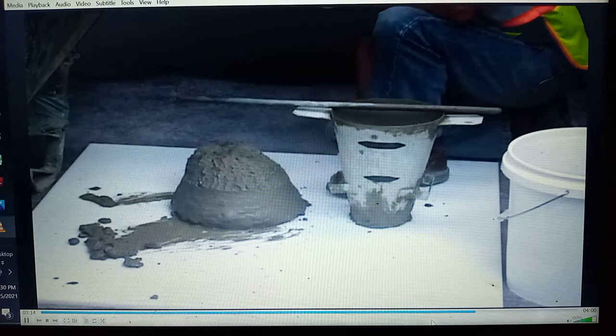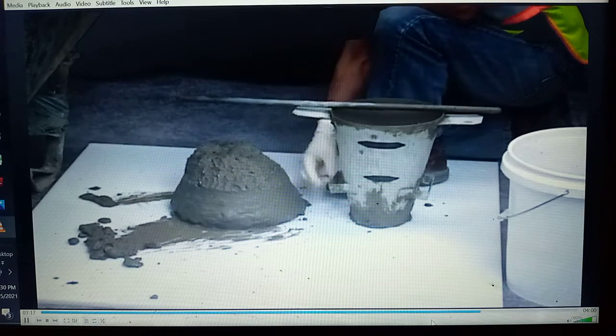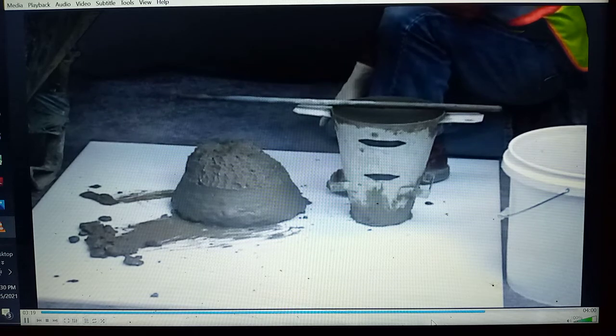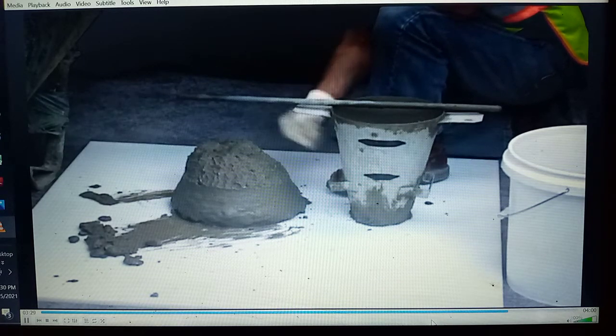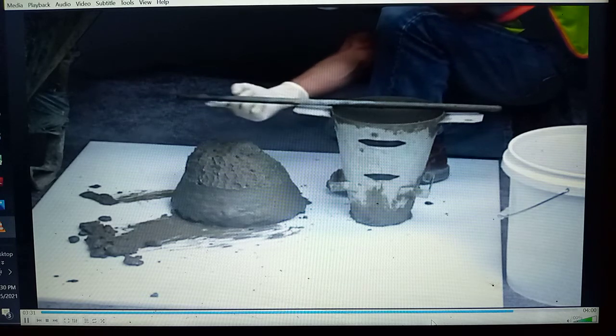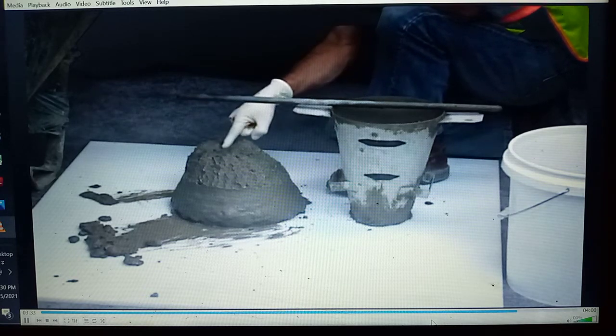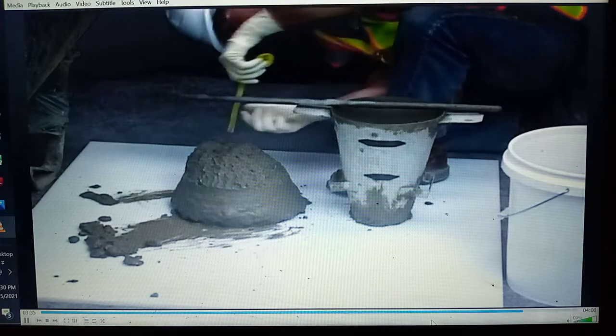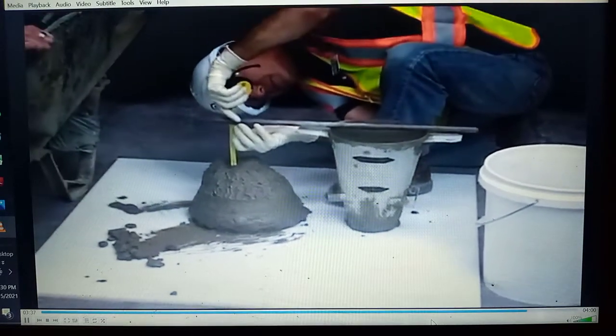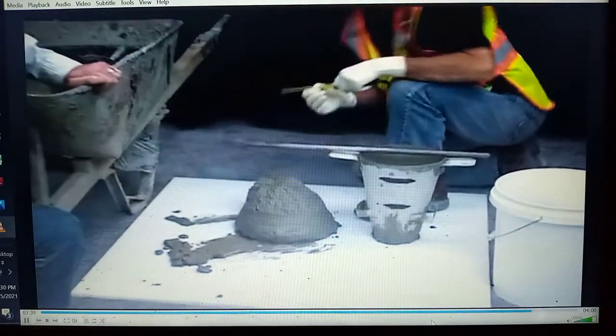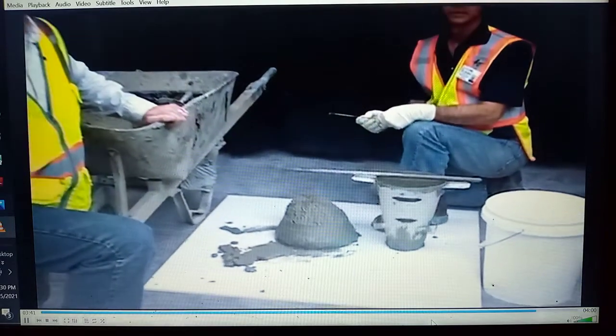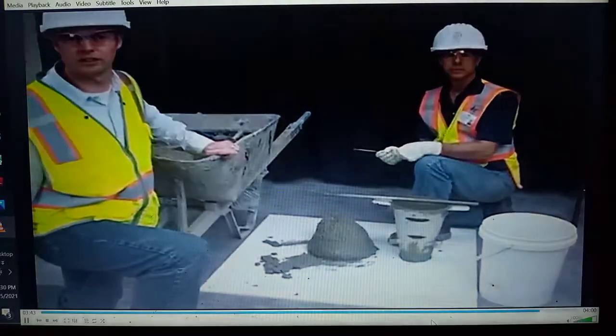I am looking to determine if the concrete is sheared off to the side. If that would be the case, this would be an invalid test, and I could rerun the test using a different sample. As we look down at our sample, that is not the case, and we can proceed. We will use the mold and the tamping rod, measuring the bottom of the tamping rod to the original displaced center to the nearest 1/4 inch. In this test, our slump is now 5 3/4 inches, and we can record the results.